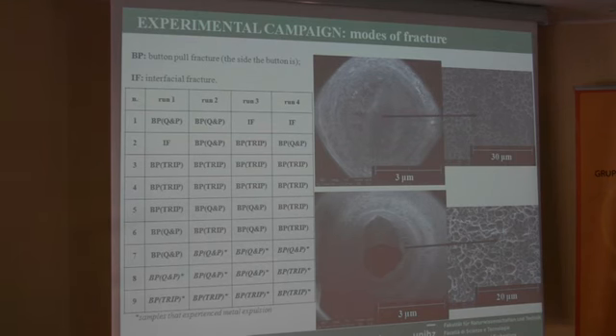Here you can see the two typical fractures that were encountered in this welded component. In particular, we found two typical fractures, button pullout fracture and interfacial fracture, that you can see here. Both the fractures were ductile fractures. You can see the formation of dimples in both the fractures.